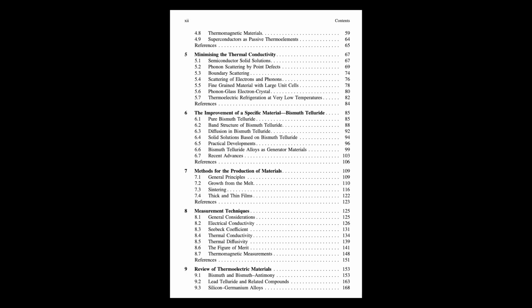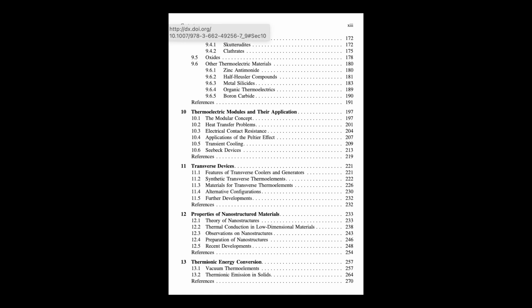Fabricating perfect structures and measuring them accurately at that scale is hard. We know nanostructuring reduces lattice thermal conductivity. What's the evidence? Yeah, there's lots of experimental proof now. Making materials from nanoparticles, nanowires, or creating bulk materials with nano features inside, like grain boundaries and embedded particles, all demonstrably lower the lattice thermal conductivity. It's mainly because all those nanoscale interfaces act as roadblocks for phonons, scattering them effectively.